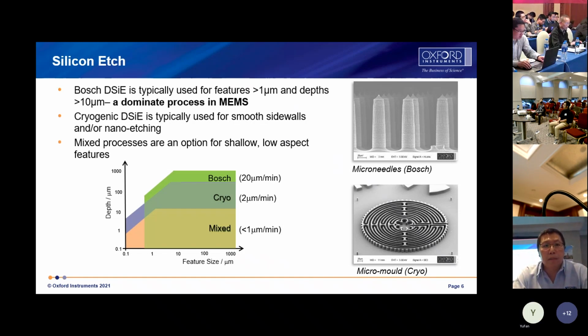The Bosch process gives a high rate, high selectivity, and a highly vertical profile, so it's the dominant process in MEMS applications. It is usually used to etch features over 1 micron with depth over 10 microns. Cryogenic silicon etching is typically used for smooth sidewalls and nanostructure etching. Mixed gas processes are another option for shallow, low aspect ratio features.